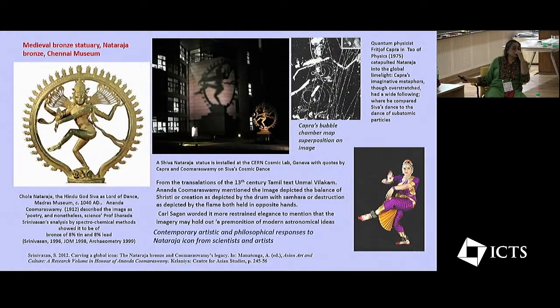And of course, you would also have seen many dances and so on, which evoke the Tandava, Ananda Tandava, and so on. And of course, I had been involved in the spectrochemical analysis of the image. And there we used the technique of taking a very, very tiny micro drilling using very fine drill bits of tungsten carbide, which is a very hard material, and then analyzing it using, in this case, inductively coupled plasma optical emission spectroscopy. And then again, it was found to be a leaded bronze, 8% tin and 8% lead.